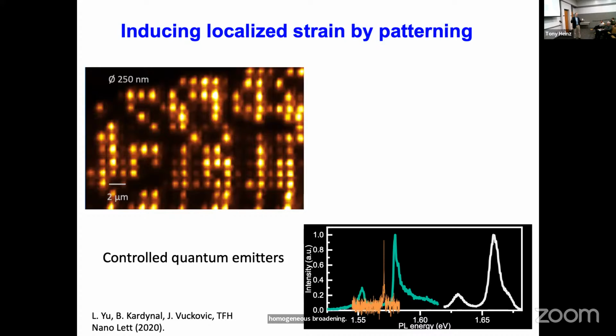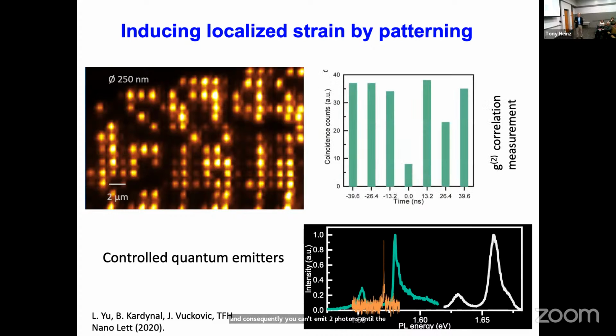But there's also a more fundamental reason, which is actually the radiative rate when you localize excitons strongly drops. They become less efficient in coupling to these outgoing plane waves. So this width that we see now is far below the radiative width you see for the delocalized excitons. And in fact, this is the regime that we call quantum emission. So in addition to the fact that you get this confinement-induced line narrowing, the trap is small enough that there's basically only room for one exciton. So you can't have two excitons in there simultaneously, and consequently, you can't emit two photons until the exciton is regenerated. And there's a standard way of showing that kind of thing, which is a photon anti-bunching experiment.